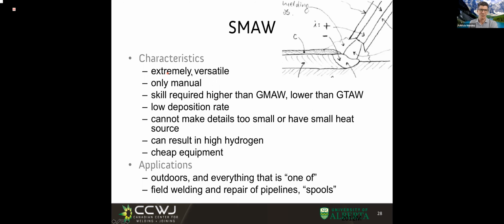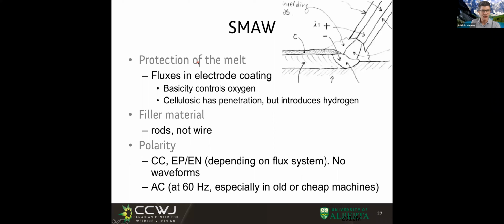Thank you. Okay, so we were talking about polarity. Constant current. Polarity can be electrode positive or electrode negative, depending on the flux system, and it comes specified when you buy the electrodes what they recommend. Typically, people do not use waveforms for a stick electrode. These are standard machines. Some machines, especially the old ones, could run on AC at 60 hertz, transformer-based machines, in which you take the high voltage, low current coming from your electrical supply and turn it into low voltage, high current for welding.